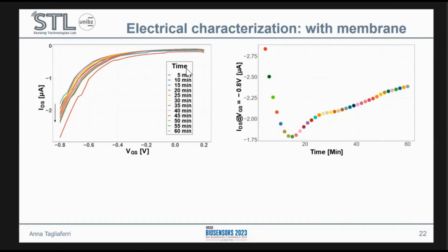and we saw that we obtained an opposite effect with respect to what we have seen before. In this case, the current increases over time. Again, to better see this phenomenon, we plotted the on current over time, and we see a very different plot with respect to what we have seen before. We see that first, we have a stabilization phase where the devices are still finding their equilibrium, after which we find the slope phase where the current increases.